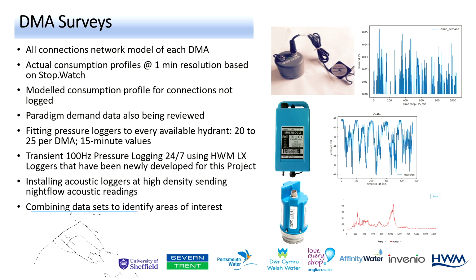We've got consumption profiles for each node, for each connection at 1 minute resolution based on our stopwatch temperature logger data and other data modelled by University of Sheffield for where we can't get a logger on. We're also now starting to review paradigm data from SME for all of the DMAs. We're fitting pressure loggers to every available hydrant, between 20 and 25 per DMA at 15-minute values. We're doing transient logging with a newly developed logger from HWM. We're installing acoustic loggers at high density, and then we're combining all those data sets.